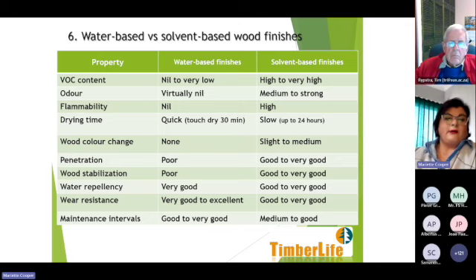And just lastly, when we talk about the new buzzword, we need to compare the two products, water-based and solvent-based, according to their properties. With reference to the VOC content, water-based varnishes tend to have null to very low content, whereas your solvent-based finishes are high to very high. With reference to odor, water-based finishes is virtually null, compared to solvent-based finishes, which is normally medium to strong. Flammability, water-based finishes is null, solvent-based finishes high.